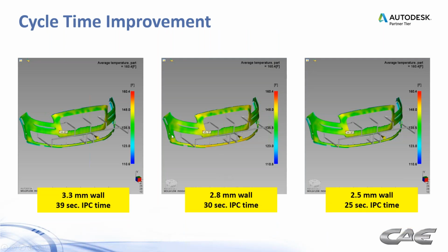To be more specific on this one, we look directly at some of the temperatures. Now, on that previous plot, that was cavity surface temperature. This is an average temperature, and we tend to look more at average temperatures when we're deciding where to end our cycle. But on the left here, we have a 3.3 millimeter wall. We have a 39 seconds IPC, meaning injection plus packing plus cooling. On the middle one there, we have a 2.8 millimeter wall, and that reduced it by 9 seconds. And then on the 2.5 millimeter wall, we're at 25 seconds, just to get everything to the same temperature. So again, this is where simulation comes in. We're able to see what the benefits are of going to the 2.5 millimeter wall.